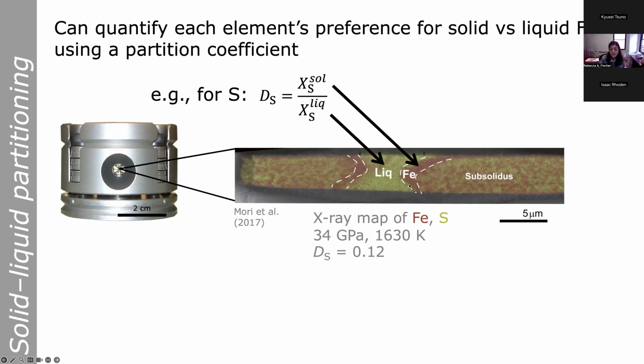So in the center here, where the laser was, is where it was melted. And you can see it's mostly this sort of yellowish greenish color. That's the map of sulfur. And the phase right on either side of the liquid is mostly red. That's where they detected iron. So in this example, there's much more sulfur going into the liquid than into the solid. So it exhibits a small value of D, something like 0.1. So that's meaning more sulfur would partition into the outer core. But D depends on a whole bunch of different variables.